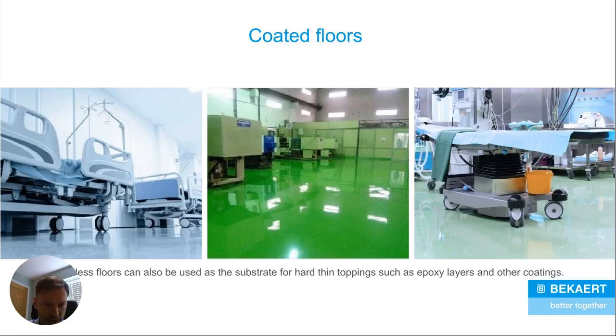Also, floors with coatings. What's important to note here is if you were to put something like a polyurethane screed or a thin resin on top of the concrete, quite often these materials cost more than the actual concrete beneath. But if your concrete slab cracks, then that resin will also crack. It's called reflective cracking. So quite often with these applications, the concrete slab beneath needs to be designed to a defined crack width.